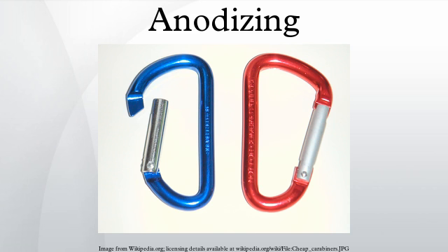Because the dye is only superficial, the underlying oxide may continue to provide corrosion protection even if minor wear and scratches may break through the dyed layer. Conditions such as electrolyte concentration, acidity, solution temperature, and current must be controlled to allow the formation of a consistent oxide layer. Harder, thicker films tend to be produced by more dilute solutions at lower temperatures with higher voltages and currents. The film thickness can range from under 0.5 micrometers for bright decorative work up to 150 micrometers for architectural applications.